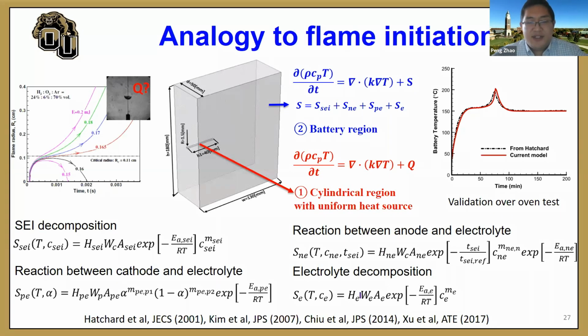So this is kind of the state-of-the-art thermal runaway reactions. And with these reactions, you can say some of the oven tests performed on lithium-ion batteries can actually be pretty accurately captured. So using this model to describe thermal runaway chemistry, we can build a 3D model of a prismatic cell, where we have a cylindrical region. We add a heat source with a certain duration, Q. And this cylindrical region is used to mimic the internal short circuit or nail penetration.